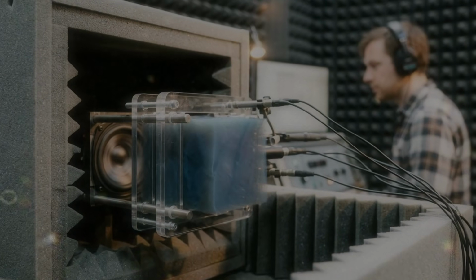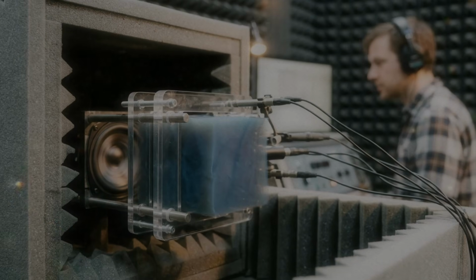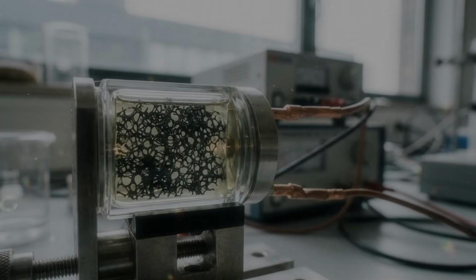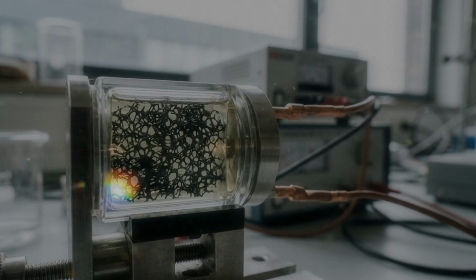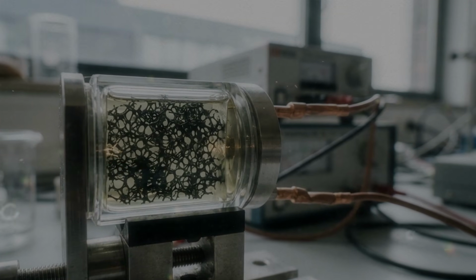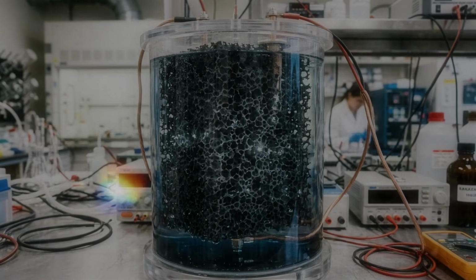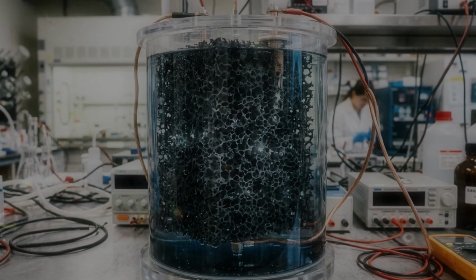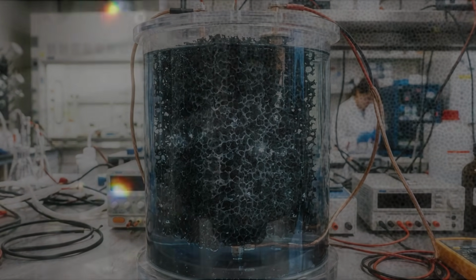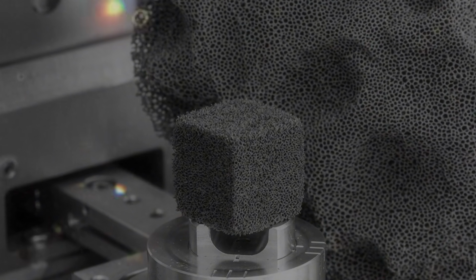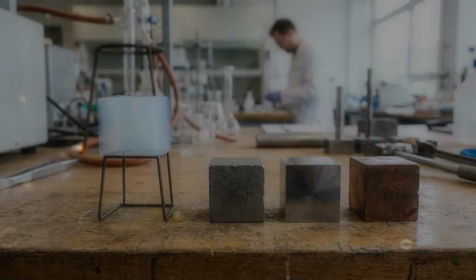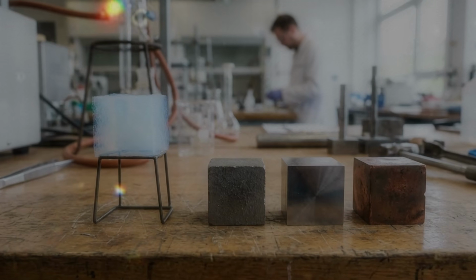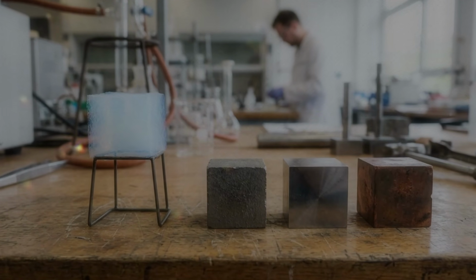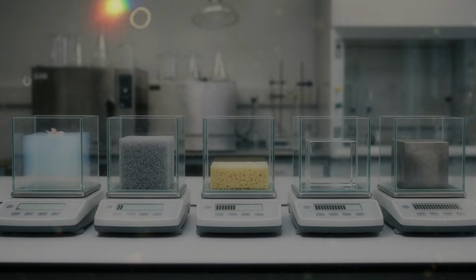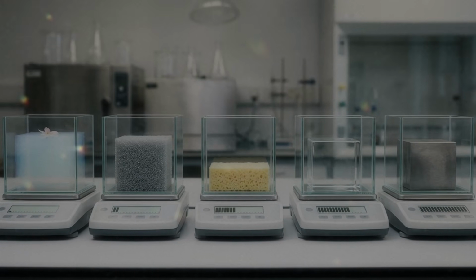For a graphene aerogel to conduct electricity, the carbon sheets must form a connected route from one side of the sample to the other. A single gap can interrupt one path, but other paths may remain available. The more connected the network becomes, the more reliably current can travel. There is a point during gel formation when separated particles or sheets first create a continuous path across the material. Before that point, the pieces may be individually conductive, but the entire sample is not. After enough connections form, the network begins to behave as one electrical structure.